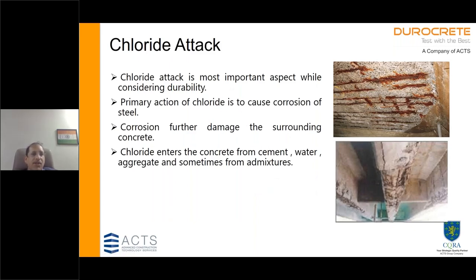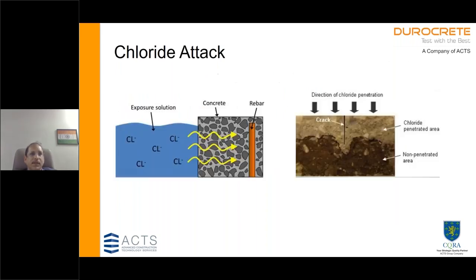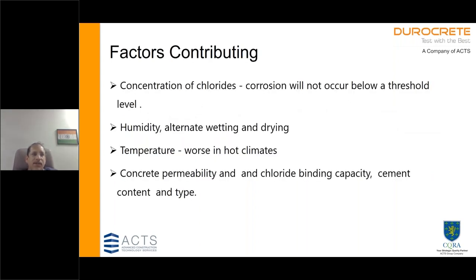We have seen chloride attack, how dangerous chloride attack can be. It also is a prime initiator of corrosion. So there is a chloride ingress, and once the chloride ingress is there, we find that there is, which we discussed, an electrochemical reaction, and it is continuous. The reaction doesn't stop once it starts. So factors that are contributing are concentration of chlorides, humidity, alternate wetting and drying. Higher temperatures lead to a faster reaction, and of course, concrete permeability is very crucial. Use of fly ash and GGBS, they build the concrete binding capacity, so they can also help in preventing the corrosion.